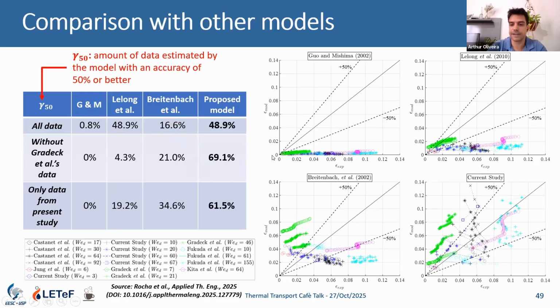And finally, the one that we fit, of course, using the fit parameters with the same data - we know about this limitation, but it's capturing the trend quite well, and we have a good amount of data well estimated within 50% accuracy.